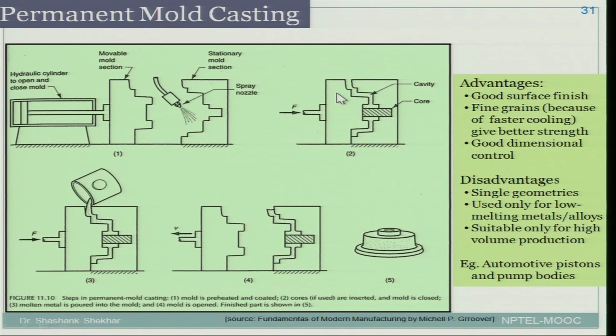Like I said, these dies are made of metals, and those metals are usually steel. So if the melting point of the metal comes very close to steel, you would not be able to pour it into it. So the metals that can be used are only those which have very low melting points with respect to the die material, and this is only suitable for high volume production. As you can see, you have made a permanent die, so you must have invested a lot, so you will be able to use it only for very large volume production.